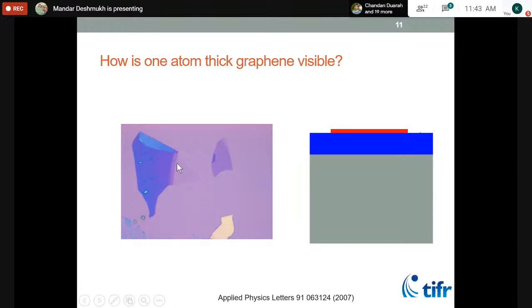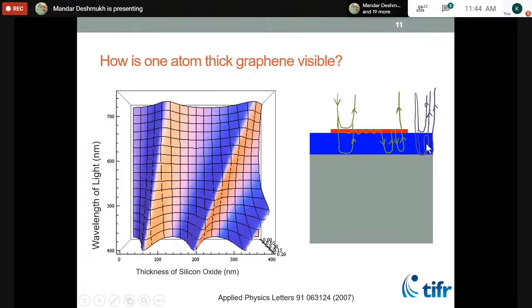Exactly the same thing allows one atom thick graphene to be seen. You put the graphene and you look at interference of light. Even though this is only a few angstroms thick, it provides enough phase shift for the light that if you look at different optical paths, you subtract the optical paths, all the possible ones, I'm drawing one possible path, you sum them up and you can see a difference. And this is a plot of the difference in the light content as a function of silicon oxide thickness, which is the thickness of the blue region.